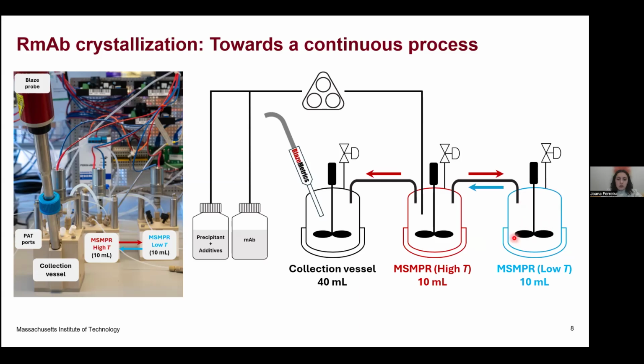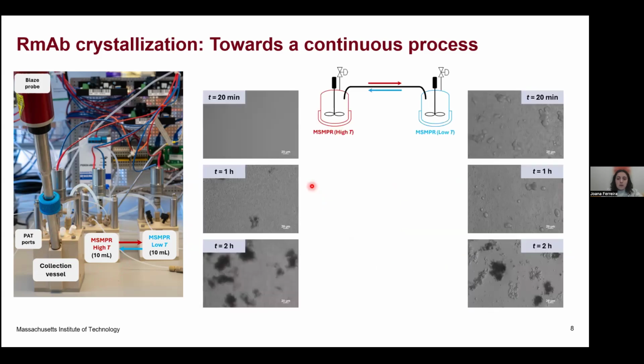So this is still ongoing research. What is also nice is that with the reactors that we are designing and developing at MIT, we also have access to different probes. For example, here the Blaze probe can give us some inline information. As a proof of concept, we tried this with one of the maps. If you compare the same time step in the hot and the cold reactor, we can already see that in the cold reactor we mostly see precipitants, while in the hot reactor we can suppress the formation of the precipitants and induce the formation of crystals.